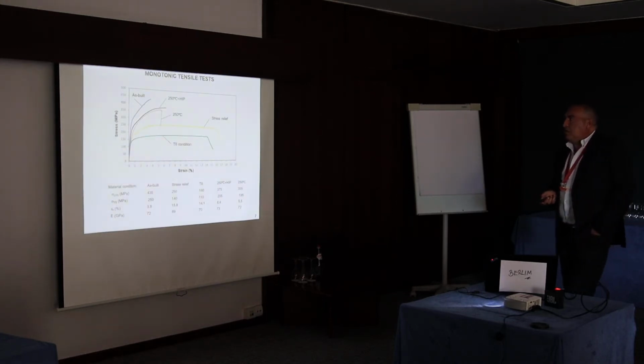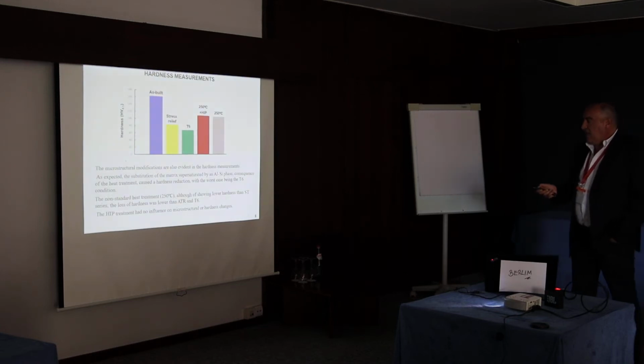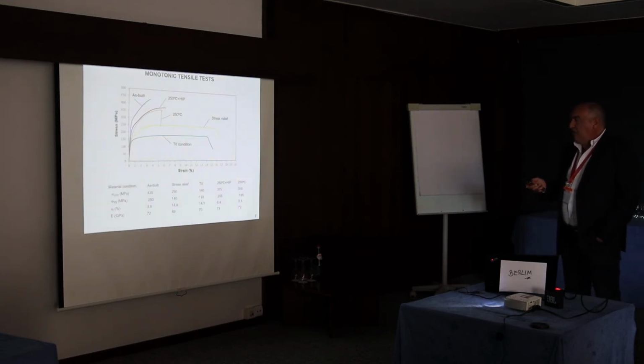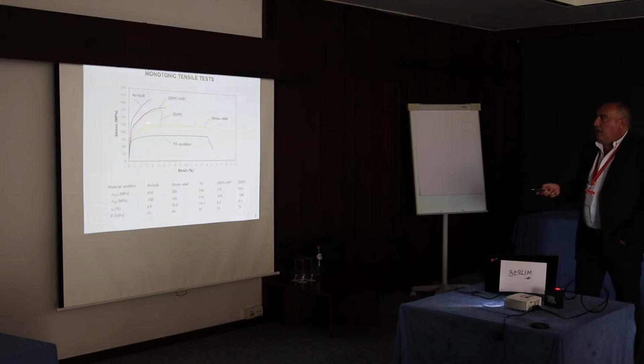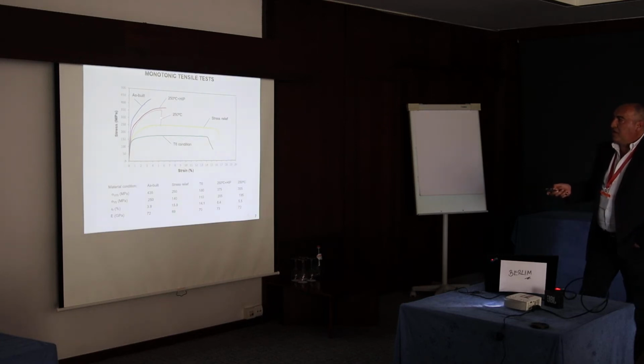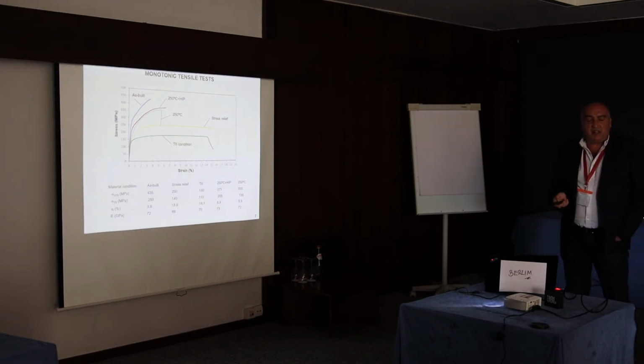Comparing the monotonic tensile tests, the difference in hardness is reflected in this figure. We can see that the T6 condition has a lower yield stress than the stress relief. Then the other 2 non-standard tests are closer to the as-built condition, although there is a decrease in the yield stress, but the strain at rupture is increased, the ductility is increased.